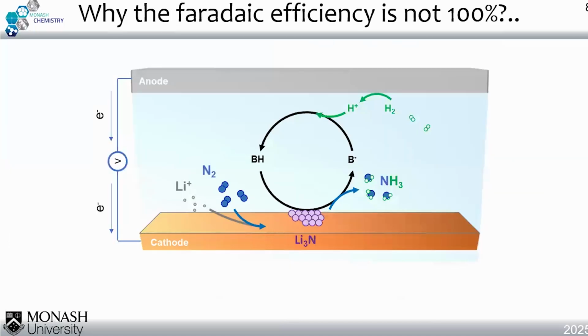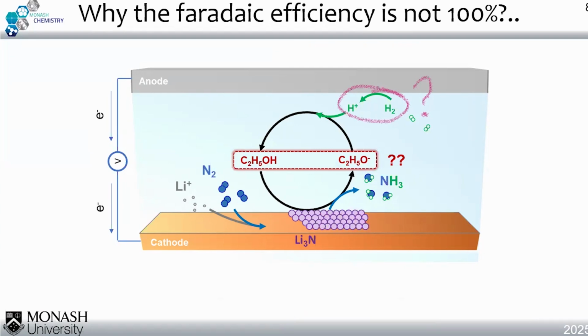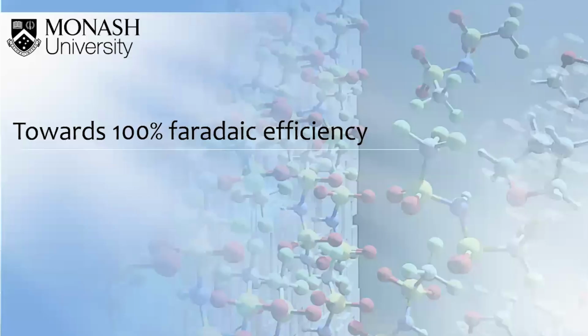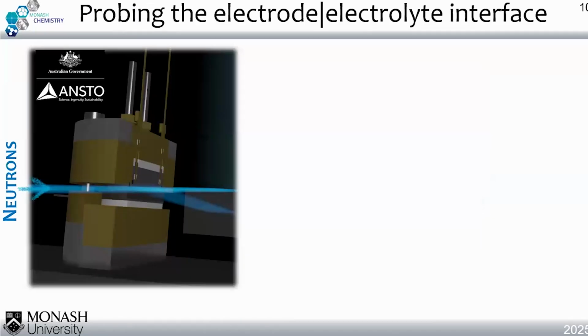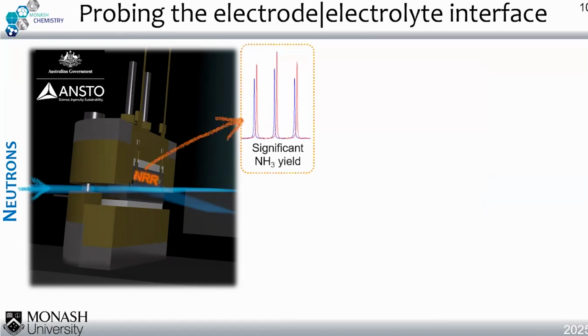There are many factors affecting the improvement of Faradaic efficiency, which are the proton source and the proton carrier, to carry the proton from the anode to the cathode, and the behavior of the lithium plating, which is closely related to the solid electrolyte interphase. So what can we do to improve the Faradaic efficiency to 100%? First we have to understand the mechanism of the electrolyte interface, so we have to probe it using neutron reflectometry. During the process, we have to quantify the ammonia and make sure we have decent ammonia and reasonable Faradaic efficiency, which is correlated with the observation of the electrode.